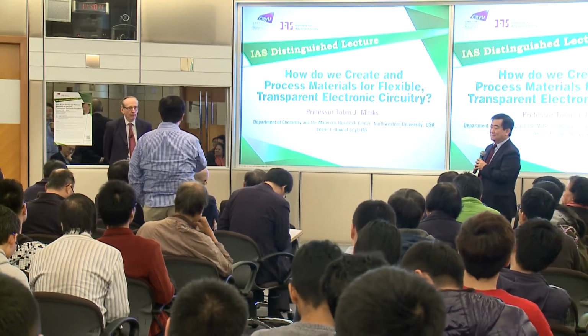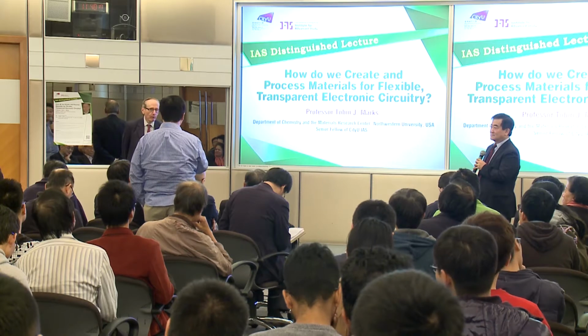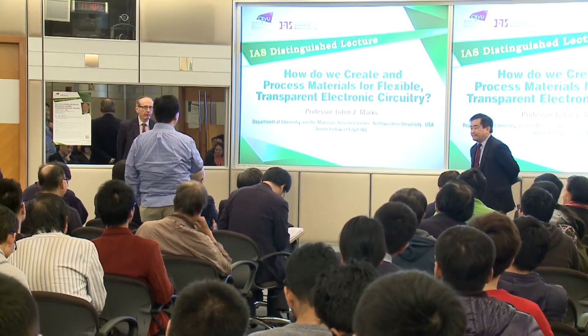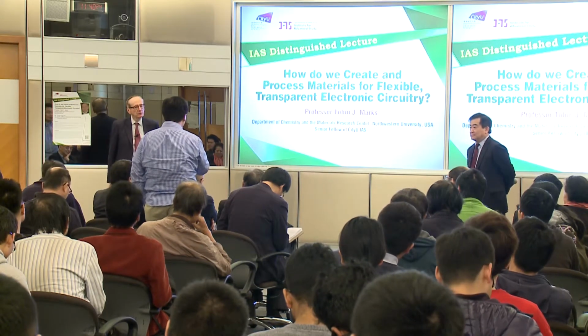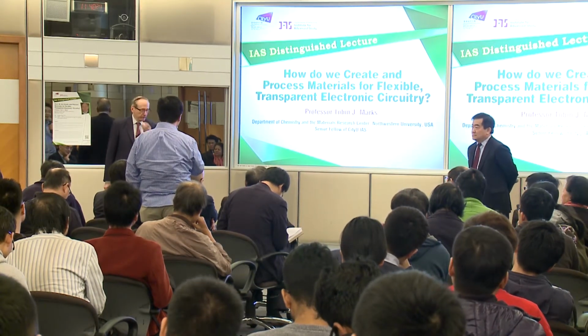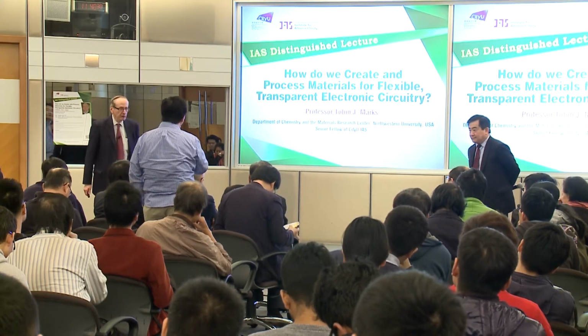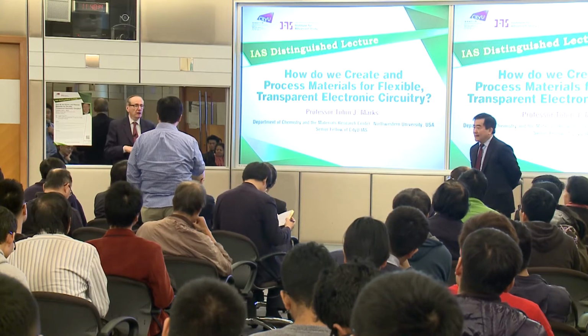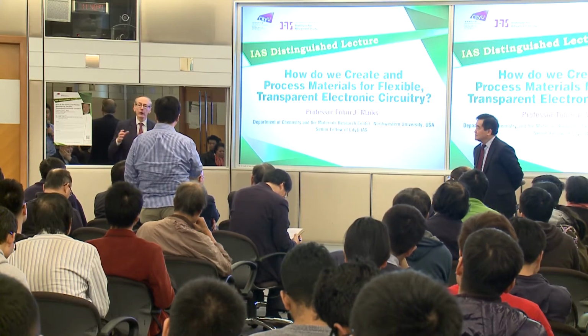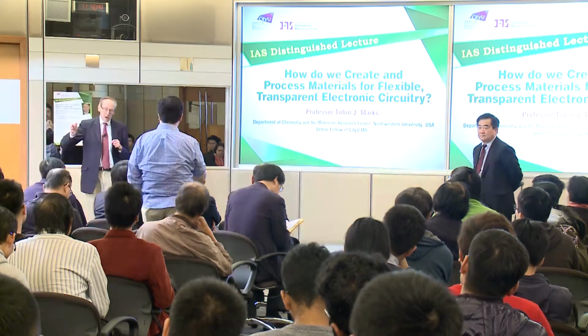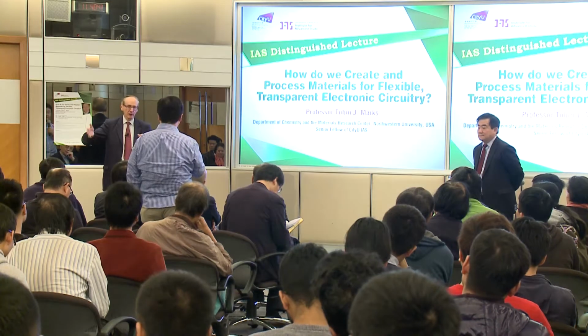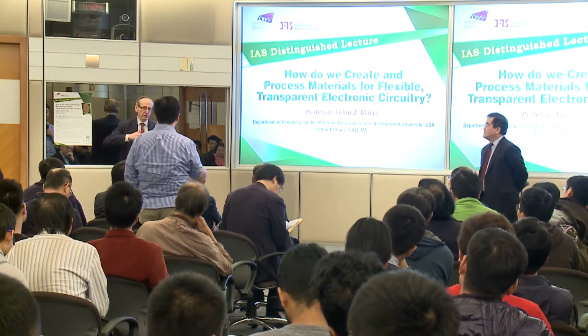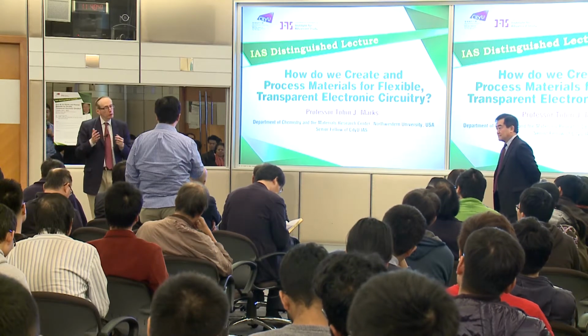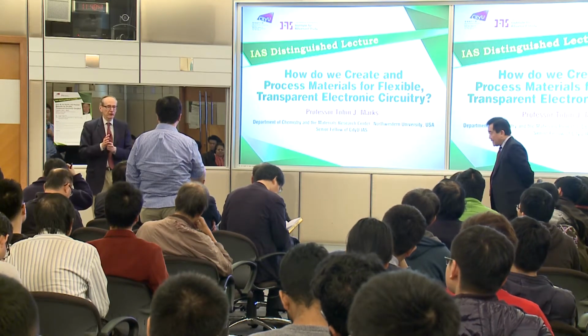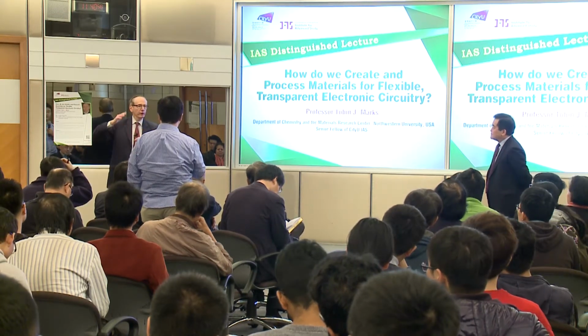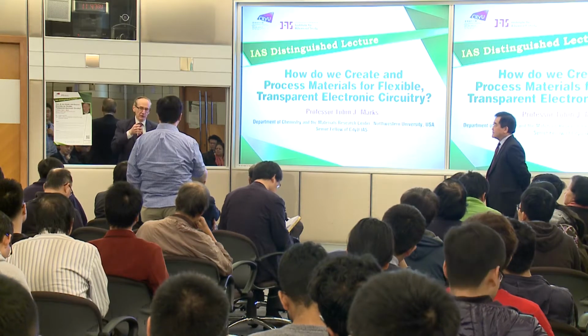Go back to questions. We talked about transistors, particularly organic transistors. One of the major issues there is threshold voltage shift, which comes with bias stress. Yes, we understand that pretty well, and you can engineer the molecules to avoid a lot of it. What it means is that if you put a lot of voltage on, chemistry starts. You're really starting to do chemistry on the semiconductor or the interface with the gate dielectric. So we routinely test for that, and FlexTerra tests for that. We've learned a lot about it, and it has a lot to do with HOMOs and LUMOs. But that's obviously a concern.